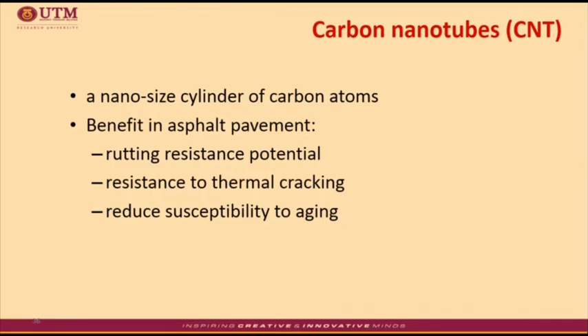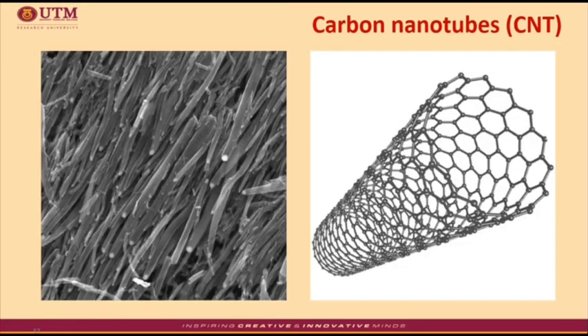rheological properties. So by using carbon nanotubes in asphalt pavement, it can provide better rutting resistance. And it was mentioned that using carbon nanotubes at 0.1% of the asphalt binder will decrease the thickness of the road layers and reduce material consumption. It also provides resistance to thermal cracking, and the addition of nanotubes has the potential to reduce susceptibility to oxidative aging for long-term performance. This slide shows the image of carbon nanotubes and an illustration of a single-wall carbon nanotube.